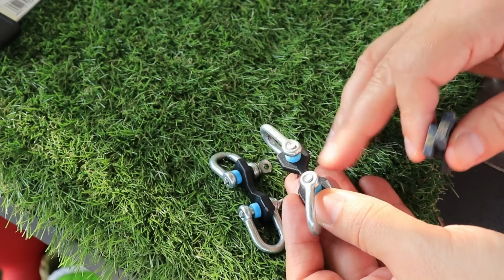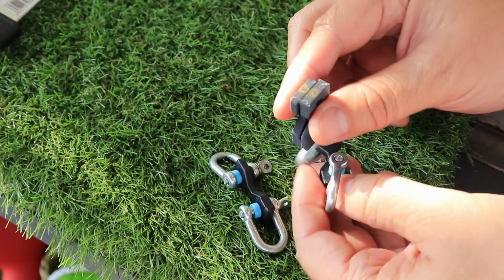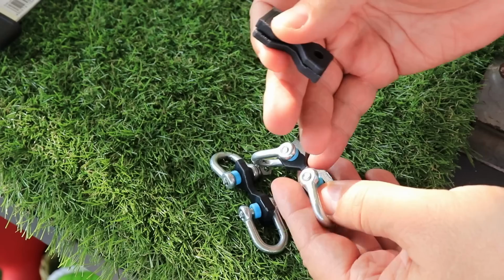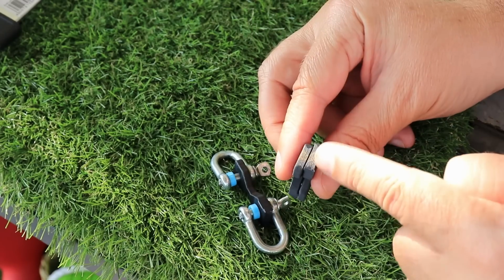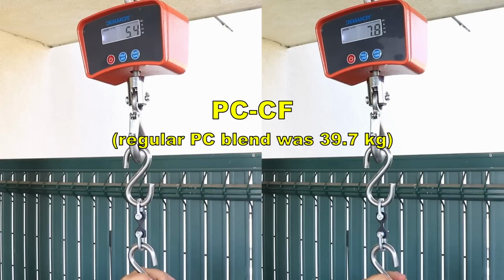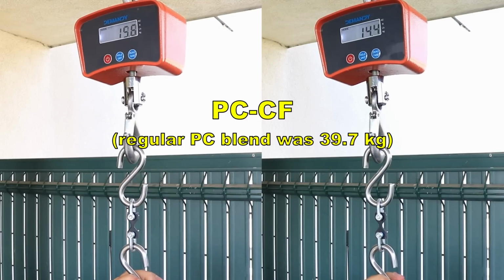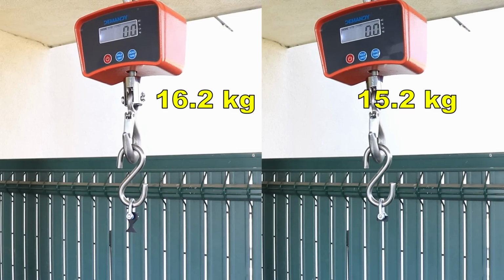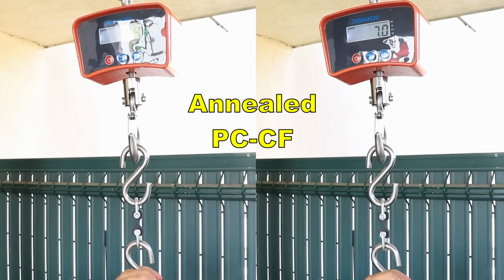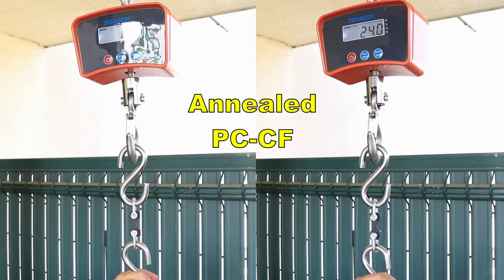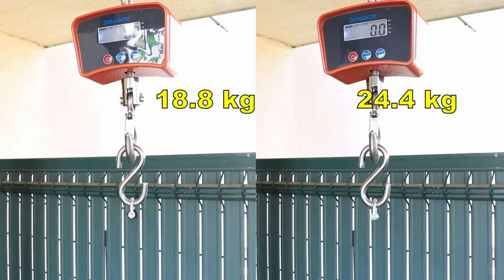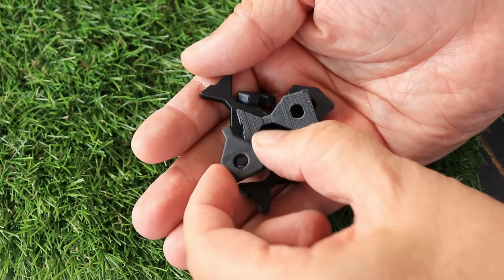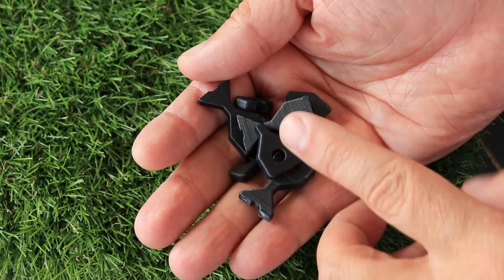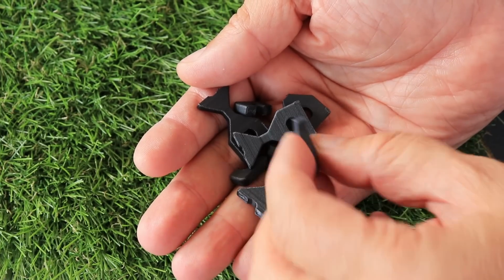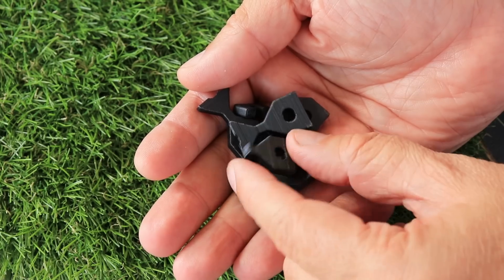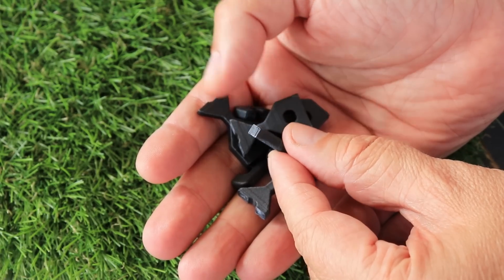And now the layer adhesion test. These test objects are printed in vertical position, and first I'm starting with carbon fiber PC blend, and then with annealed versions. Well, unfortunately, this is something I was afraid of. I still remember the feeling when I broke the regular PC blend, and I know that this is much weaker.